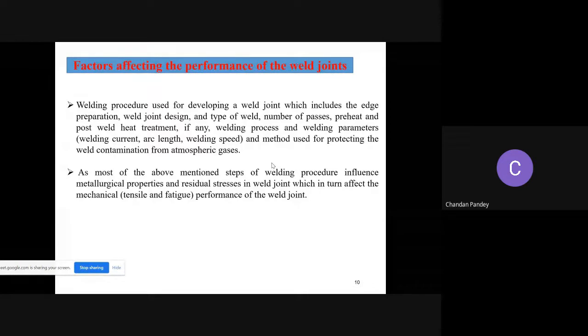After that, the other parameter that we consider is the welding process, which process we are going to use. Generally, in the case of aerospace applications, we don't prefer to add additional material. So in that case, we use advanced welding like activated TIG welding, or friction stir welding, where we don't use filler metal that would increase the weight. And if you talk about power plant, chemical and petrochemical industry, here we use the multi-pass TIG welding process, where the plate or joint thickness is more than 10 mm.